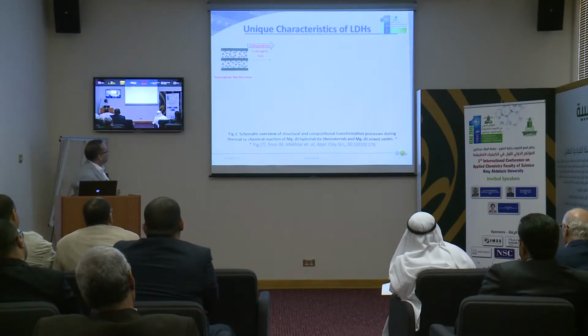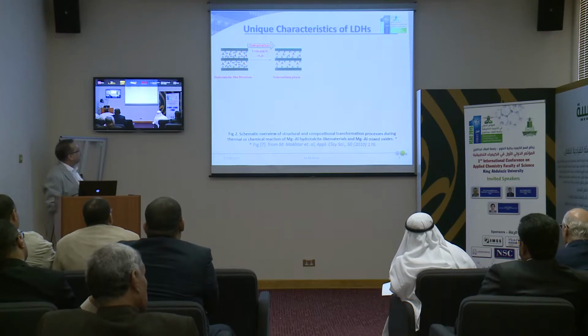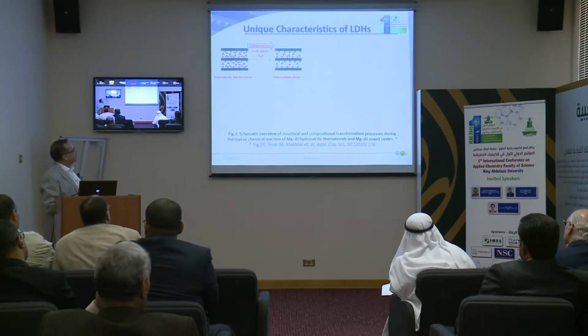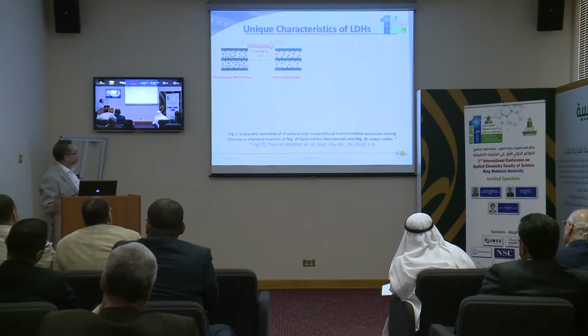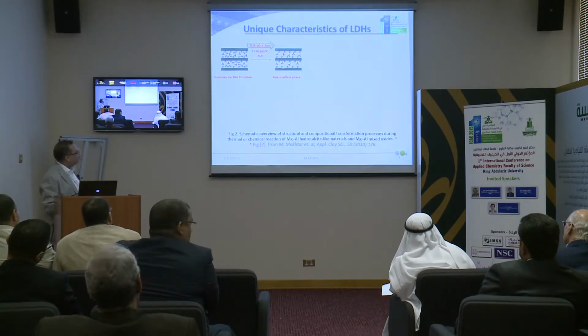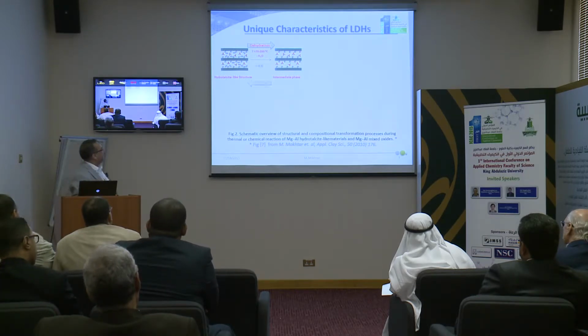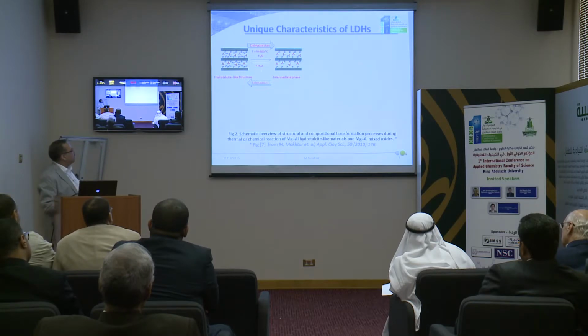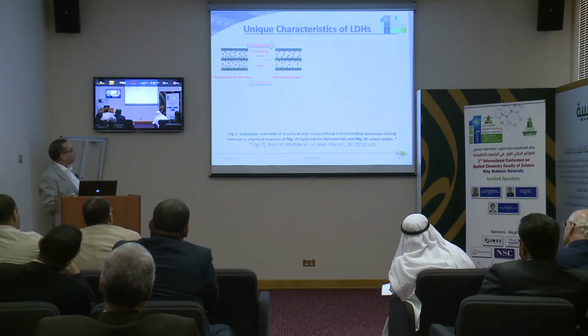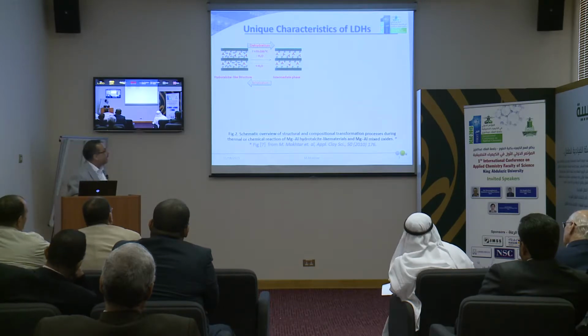It's just dehydroxylation of the material, so we can keep the structure of the cations itself without collapsing of the structure. In this stage, which is the intermediate phase, we can return back again by what's called the rehydration process, where the structure is completely kept and returned back to its original position.